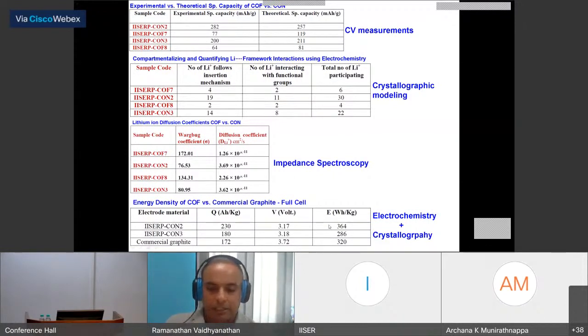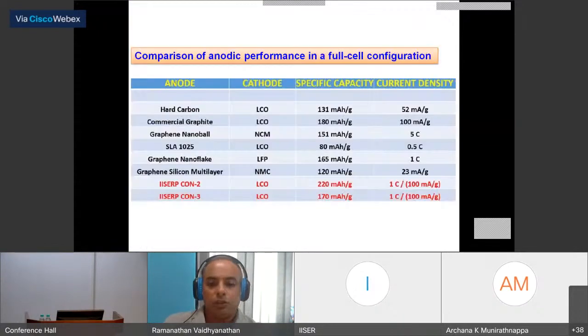I think there was a mistake in the previous slide. So this is the energy density that we can see. The commercial graphite has an energy density of 320 watt hour per kilogram, whereas the COFs have 364 watt hour per kilogram, which is spectacular. And this is possible because of the combination of electrochemistry and crystallography. So we also compare it with all the other types of commercial materials, and the COF-based battery anodes are pretty good compared to many of them. Even at high current densities, they are able to do pretty well.